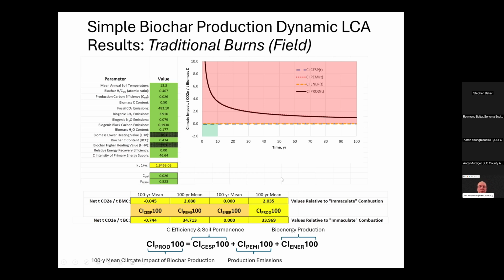When you add these up, you get numbers down here, highlighted in yellow. And what I typically do is report them in terms of tons of CO2 equivalent per ton of biomass carbon. So in this case, that's a little more than 2 tons CO2 equivalent per ton of biomass carbon relative to immaculate combustion. I'll show some numbers later that give you an idea, if we didn't ratio it to anything, what the absolute carbon emissions would be. They'd be about 1.91 tons of CO2e higher, because immaculate combustion is about 1.91.